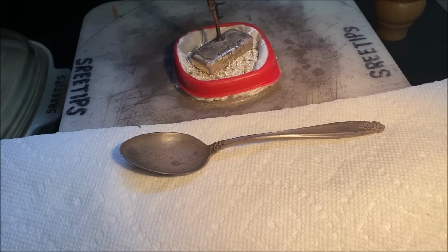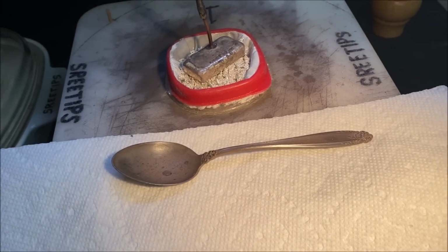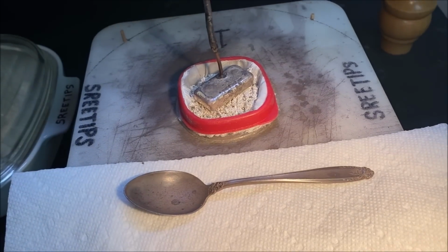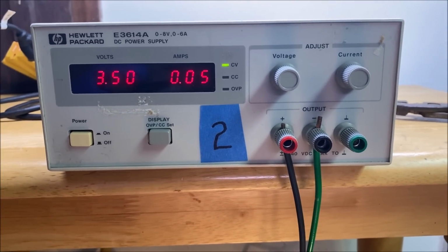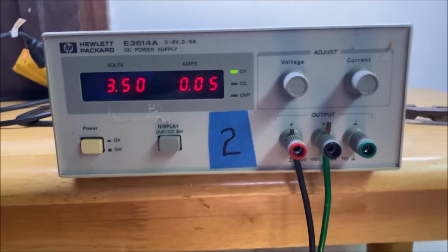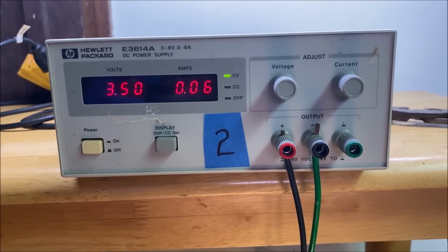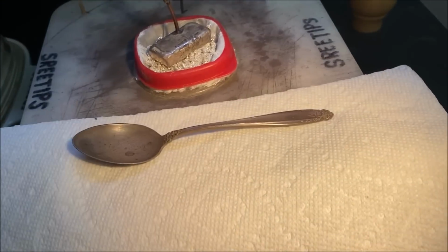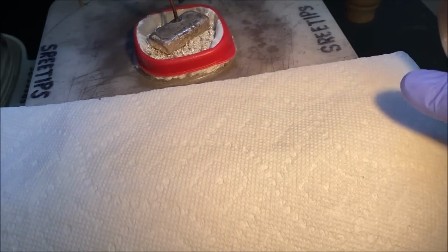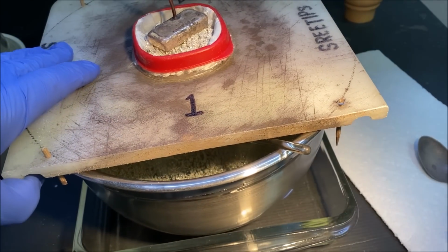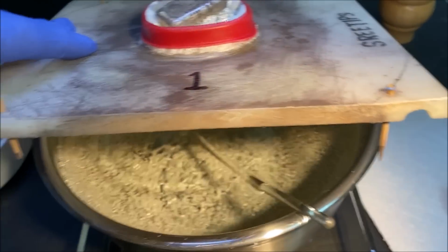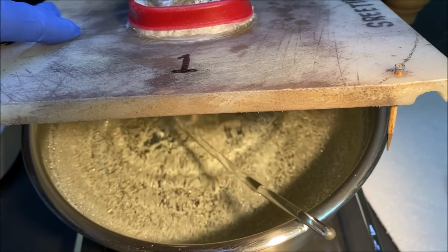SREETIPS here, and this is the experiment that we're doing, running the pure silver crystal back through the cell a second time. If you look up here, you'll notice that the amps have fallen way off. This thing's been in operation now for about 9 hours, I think, 8 hours. And here's what we've got for crystal growth going on down inside the cell right now. Looks good.